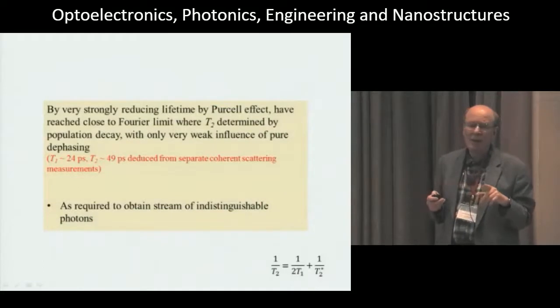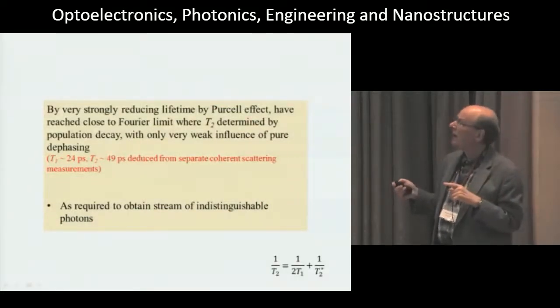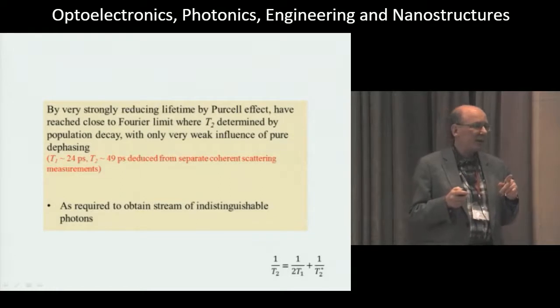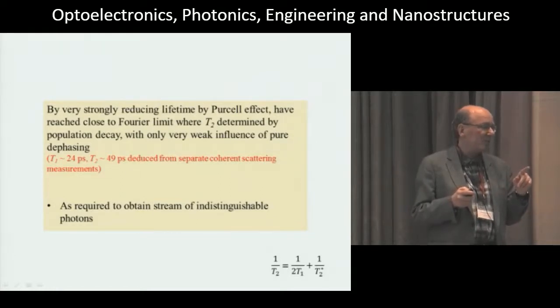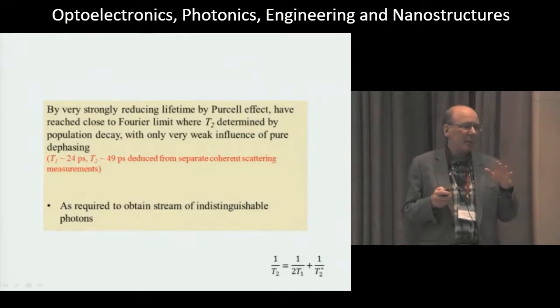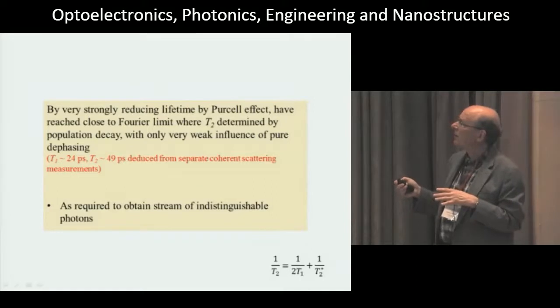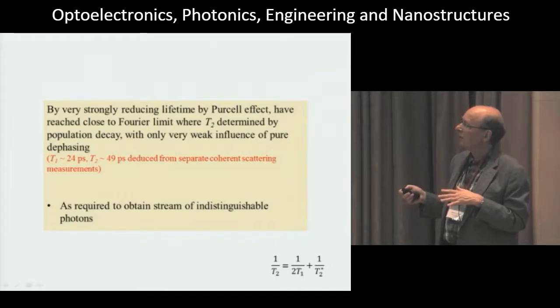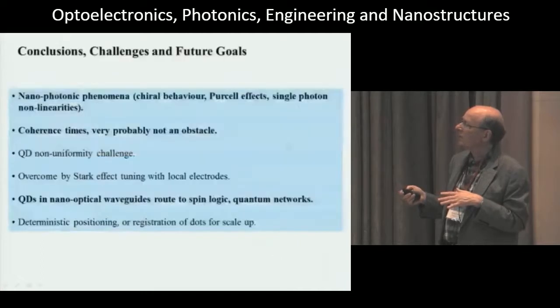And we've achieved this, to say it once again, by the Purcell effect. So we've reached very close to the radiative limit where T2 is determined by population decay. So it's determined by intrinsic properties of the quantum dot and not by dephasing effects in the environment. So we've made T1 very much smaller than any effects of pure dephasing. And in separate measurements, we do indeed find that T2 is equal to 2T1, as required to obtain a stream of indistinguishable single photons.